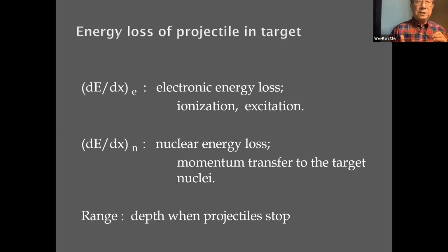So what are you touching? You're touching the electrons. Although those are orbital electrons, to you it really doesn't matter. They are negative particles. Do they slow you down? Yes, they do, because the ion has positive charge and the electron is negative, so there's a Coulomb interaction. Also, some electrons gather behind you and try to follow you as you travel very fast.